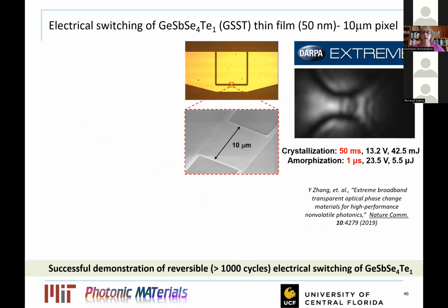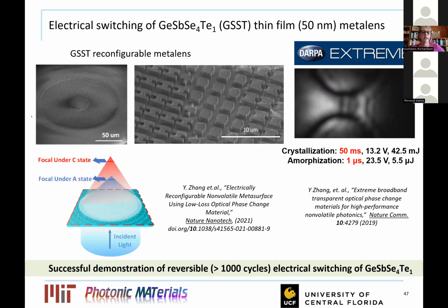Well, working with the MIT team and our partners through our DARPA program, we made a compositional modification to the GST and showed that by reducing the amount of tellurium by substituting another chalcogen, selenium, we could make a GSST alloy, which has very low loss in the infrared and switches very nicely over a wide variety of applications. So here's an application now of this phase change behavior, and the movie that was showing here illustrates the active switching in this very central region where there was a heater, and the powers needed to do that switching.